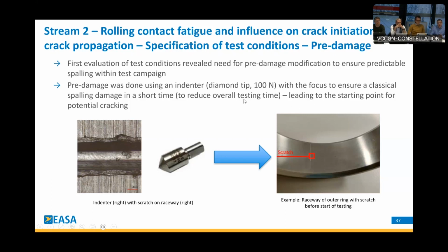And this was done by an indenter with a diamond tip and a force of 100 Newton. So we can, in each test, ensure a classical spalling damage in, I call it short time, but it's an overall testing time that we needed to do all the tests in this project. And this was leading to the starting point for the potential cracks, crack growth, through cracking, and so on.